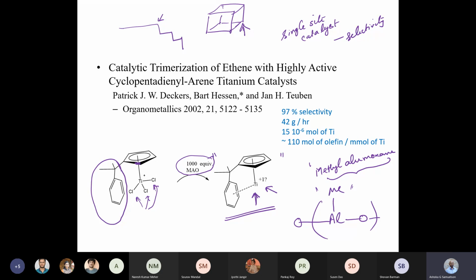So this species can take up a lot of Lewis bases. So any X minus that comes can coordinate to this aluminum. So it is a sponge for any Lewis base, including traces of moisture or residual oxygen. It will just remove every species which has got a lone pair of electrons. As a result, the titanium is left uncoordinated. That is why I said that you have this vacant coordination site on titanium. And the only thing that the titanium gets its hold on is the olefin. So it activates the olefin and makes it very reactive.